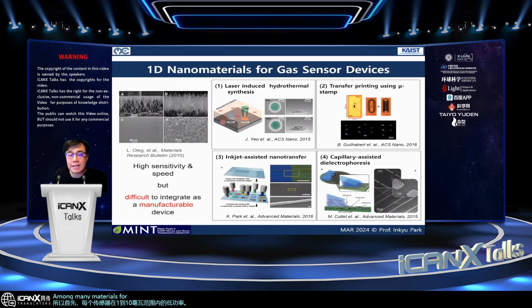Among many materials for the semiconductor metal oxide gas sensor, one-dimensional nanomaterials such as nanowires or nanofibers have been very useful because they have large surface area to volume ratio, high chemical reactivity, and high response speed. However, the biggest problem of one-dimensional nanomaterials for the gas sensor device was the integration of these materials on the device platform. Usually, chemical synthesis is used for the fabrication of these nanomaterials, but they have to be somehow collected or harvested from the substrate, then deposited or printed on the electrode for the device fabrication. However, they're quite difficult to integrate as a manufacturable device in a repeatable and high throughput